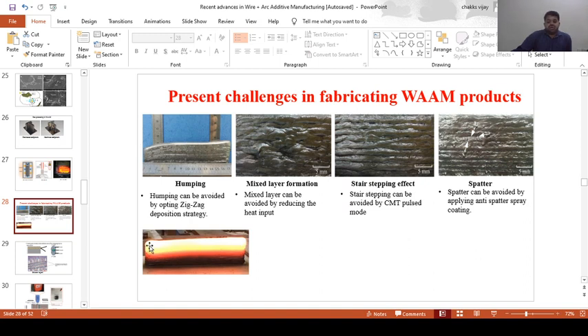Until then we should be patient enough. Especially when it is in molten or red hot condition and we deposit a subsequent layer, it will lead to this kind of humping effect. So if we want to avoid it, we can maintain the interpass layer temperature, or else, in case we couldn't properly maintain the interpass layer temperature, you can go for zigzag deposition.